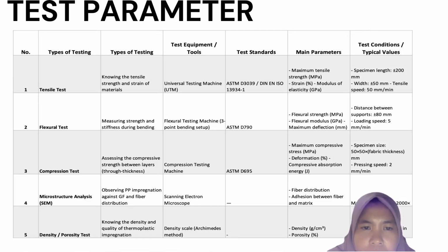Parameters: maximum tensile strength and modulus of elasticity. Test conditions: specimen width 50 millimeter, tensile speed 50 millimeter per minute. Two, flexural test: measure strength and stiffness during bending. Tools: flexural testing machine. Test standard ASTM D790.